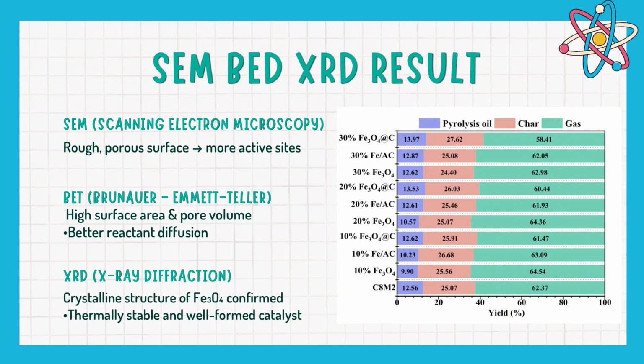overall catalytic efficiency. Finally, XRD or X-ray diffraction confirmed the crystalline structure of iron oxide inside the carbon matrix. The clear diffraction peaks match well with standard iron oxide patterns, indicating the catalyst was well formed and thermally stable. Together, these results show that the catalyst is structurally suitable, chemically active, and physically stable for microwave pyrolysis.